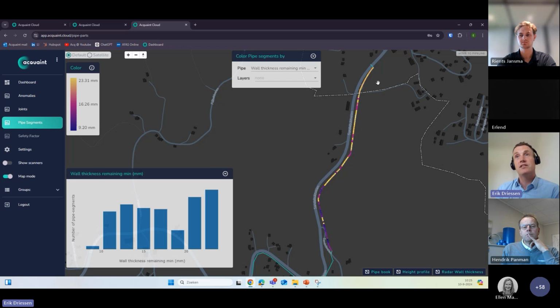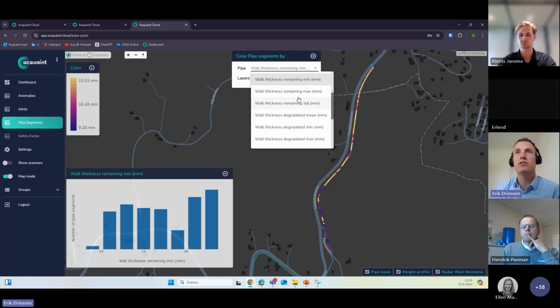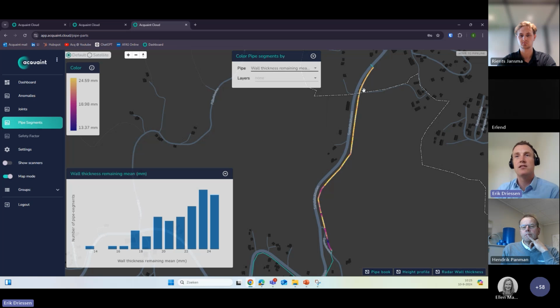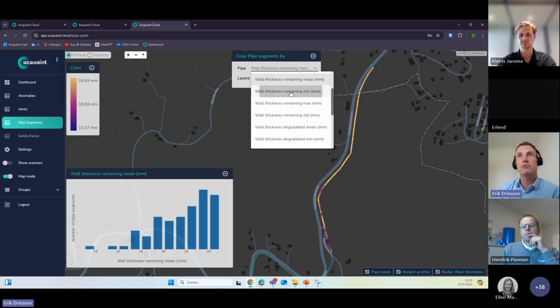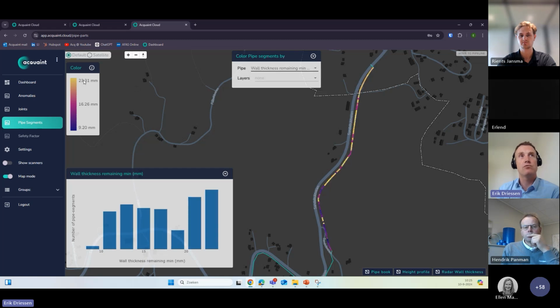Again, let's look into the wall thickness, the minimum wall thickness, just after launching the pipe book. Now, let me also show you the mean one. That makes it a little bit less dramatic. So the mean wall thickness ranges from 13 to 25. But when I look at the minimum, that ranges from 9 to 23. So this is also the conclusion: the thinnest little spot of remaining healthy wall thickness of the AC is just 9 millimeters.